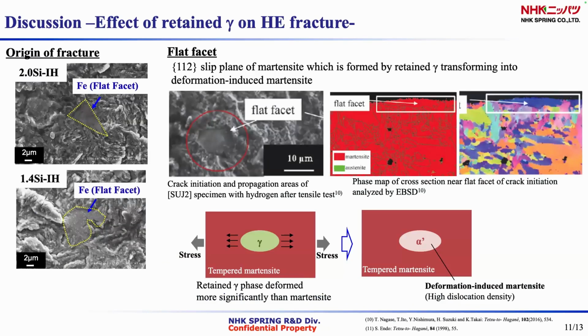And next, I explain the effect of the austenite on hydrogen embrittlement. We thought the origin of fracture of IH tempered steels was a flat facet. This is a previous research. There is a lath phase at the origin of fracture, which exhibits a {112} plane on the fracture surface. The authors assumed that when stress was applied to the specimen, the retained austenite underwent deformation-induced martensite transformation. The martensite is highly sensitive to hydrogen embrittlement, so it becomes the origin of fracture. In this way, we thought that retained austenite was the fracture origin.